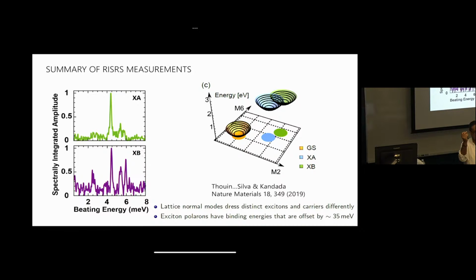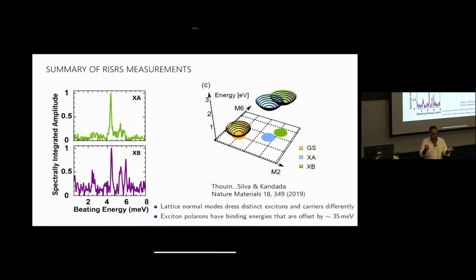And at 5 Kelvin, electron and hole recombine into XB. Let's say you want to make an LED, a light-emitting diode. What is your emissive state? You inject electron hole. Within a picosecond at 5 Kelvin, they recombine into exciton B. Then within tenths of picoseconds, they relax to exciton A. And that is a radiationless relaxation, a so-called non-adiabatic relaxation that produces the lowest exciton state. That's your emissive state in the LED.